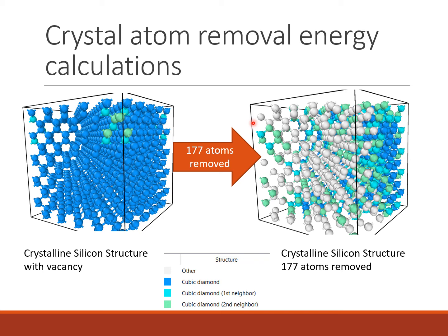This is in contrast to the expectation of the algorithm, which would have been that it would contract back to crystalline silicon. Instead, we see that amorphous silicon, this unordered structure, emerges as we remove more and more atoms, and we get more and more negative vacancy formation energies.